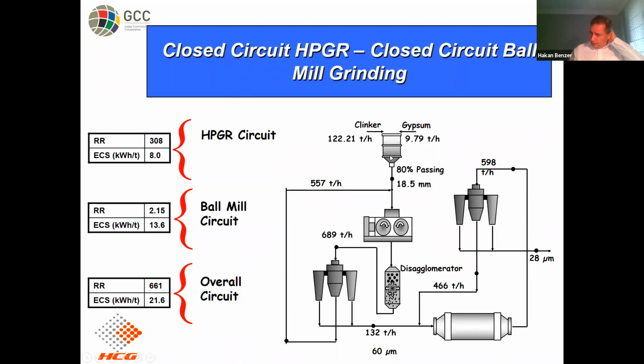Here, you see the feed going into the system is 18.5 millimeter F80 size, and comes down to 60 microns just in an HPGR circuit. We are talking about a reduction ratio of, roughly speaking, 300 at 8 kilowatt hours per ton, including the fans, the classifier, and the main motor. So significant work is being done with the high pressure grinding roll system. And this is typically fine.